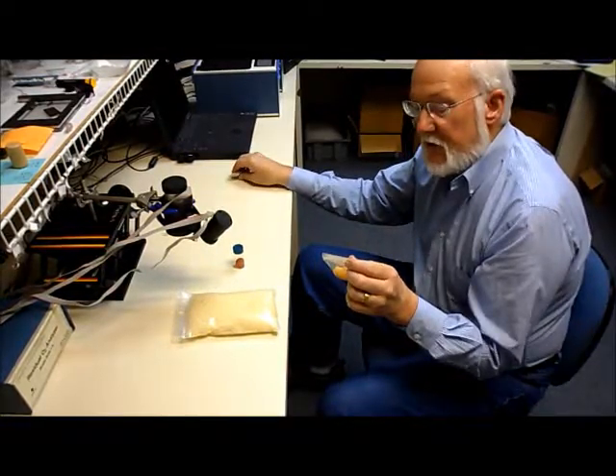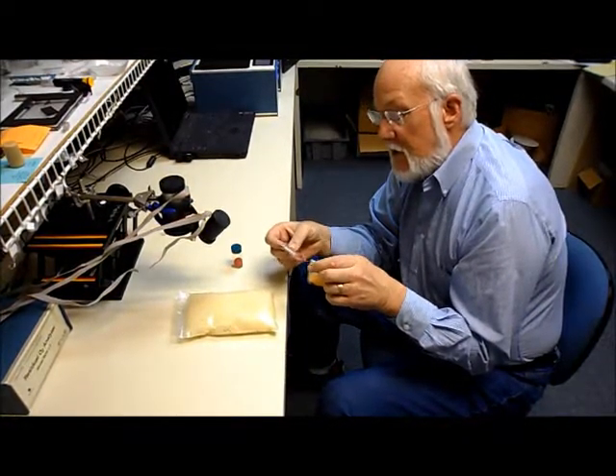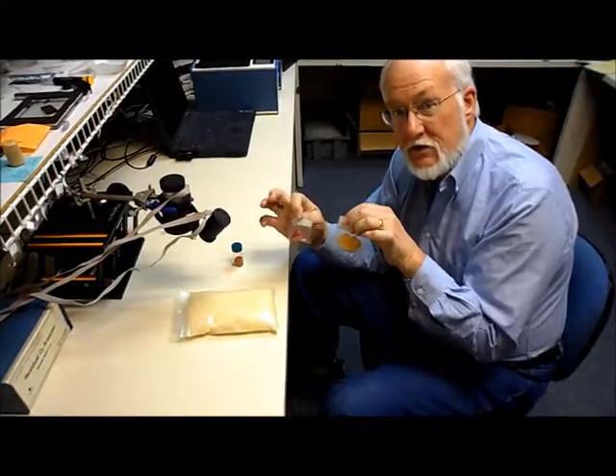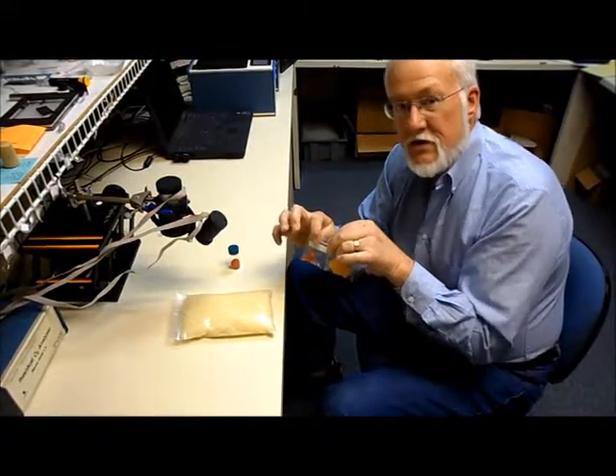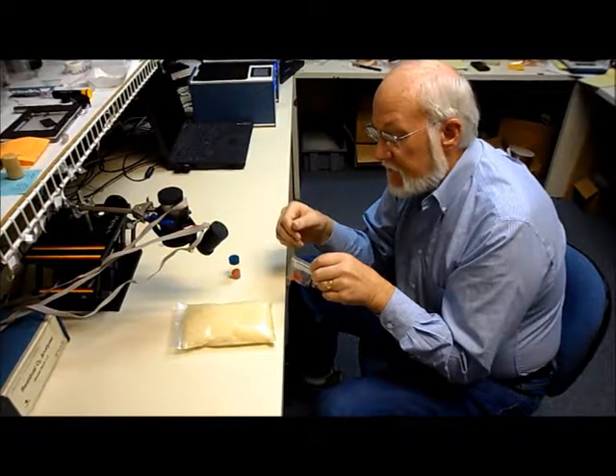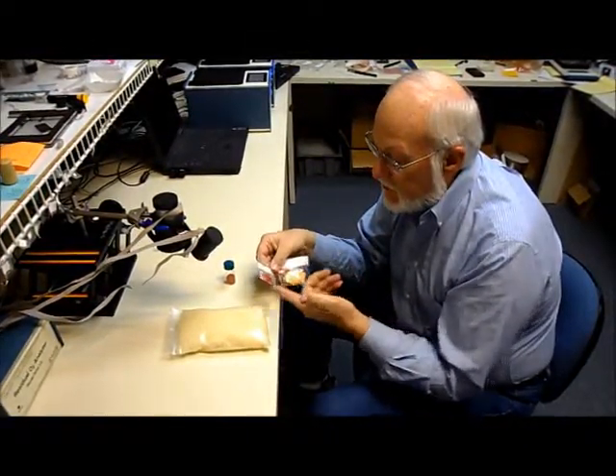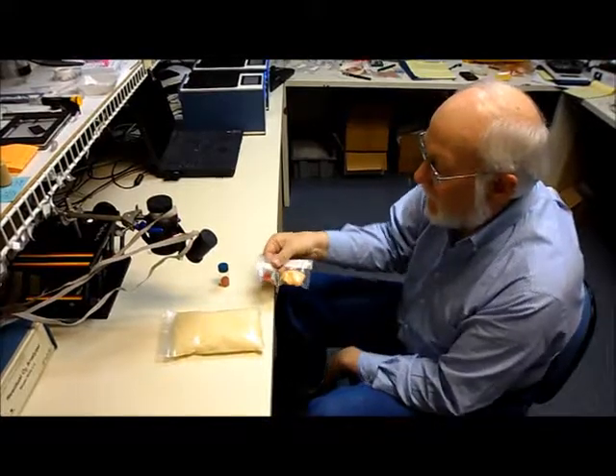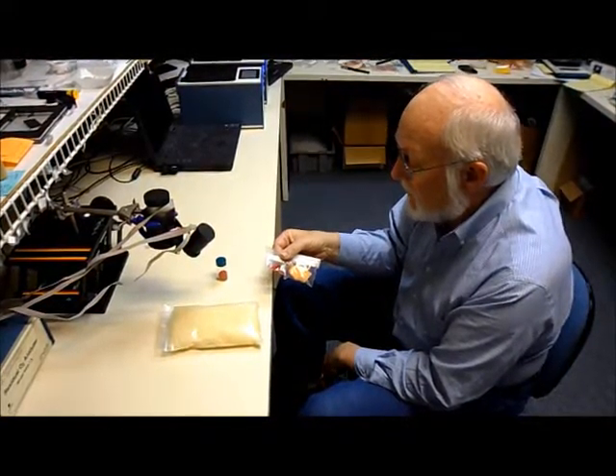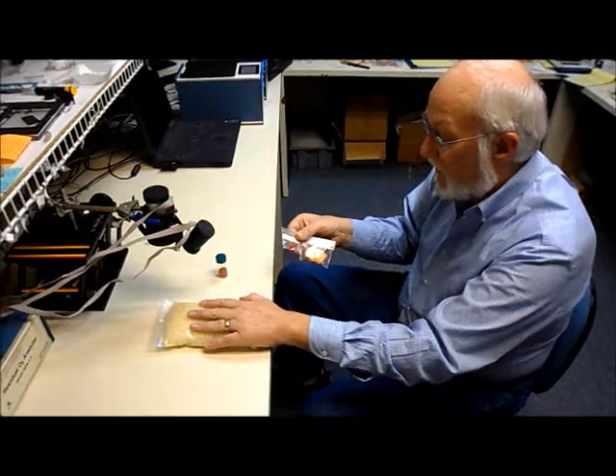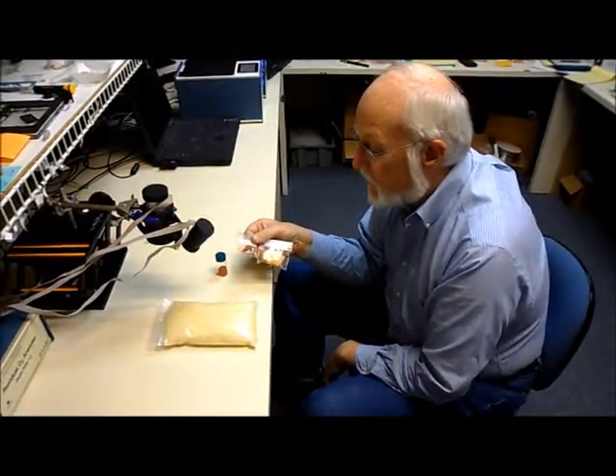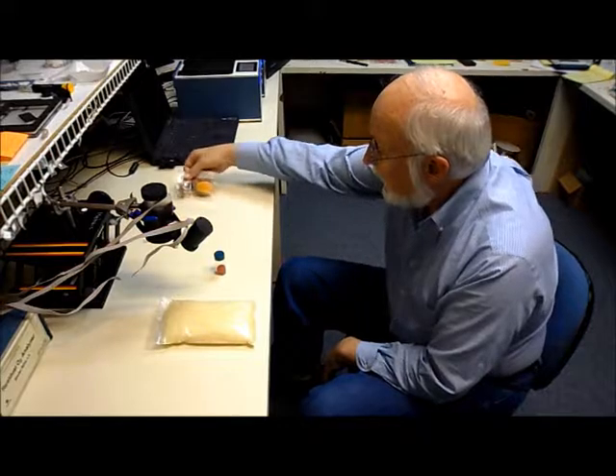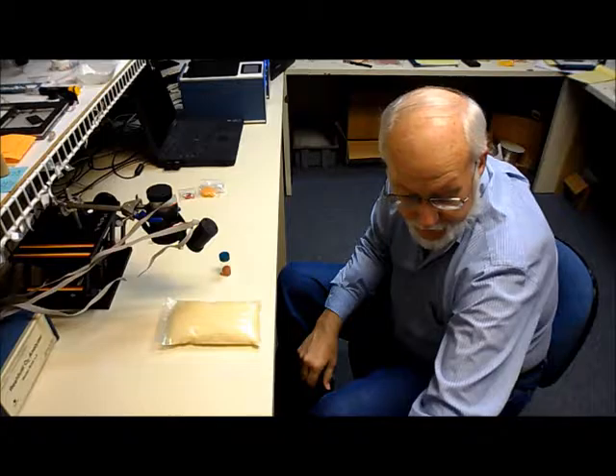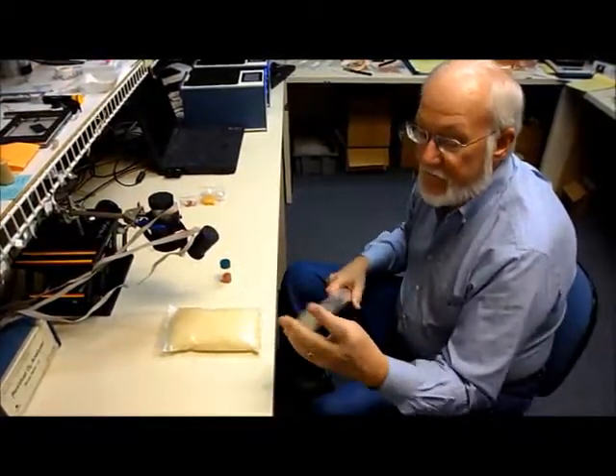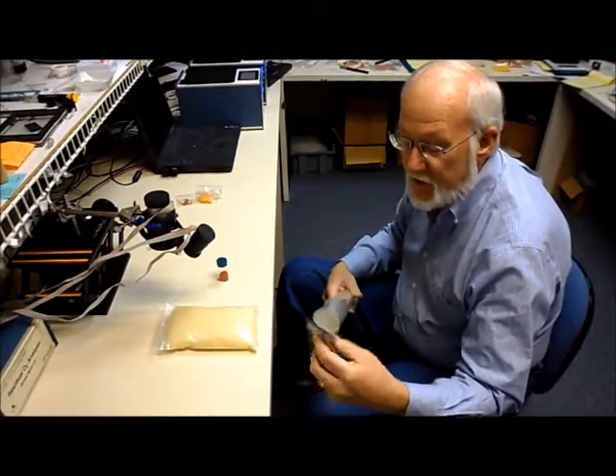But I've got an example here of two different dyes that I'm showing you. They are distinctively different colors. They're different oxygen sensing compounds which we've selected for their different properties, and each has been introduced, as I call it, at least a small example of a master batch, where it is by melt process mixed with polymer. And then, as I was referring to, the polymer can be extruded into rolls of thin film, multi-layer laminates, barrier films, etc.